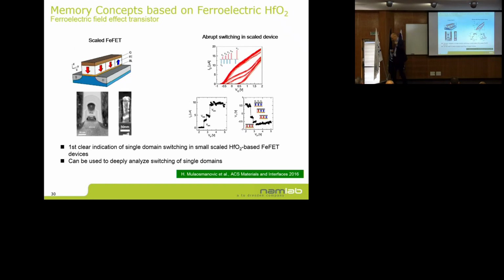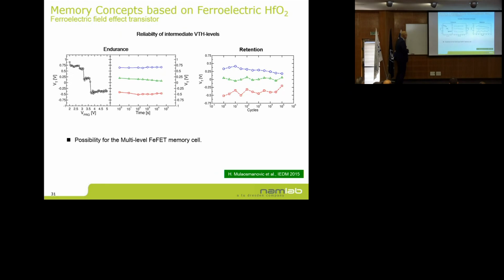Once you have these small transistors that were never possible with other materials, all of a sudden you see steps in the programming curves. And we attribute this to switching of single domains. It's not fully proven yet that these are single domains, but it's very likely that this is. So you can also use this type of devices to study the ferroelectrics more deeply. And even these steps are very, very stable with respect to endurance and retention.